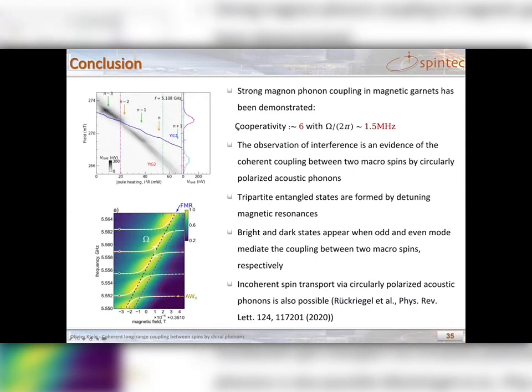So in conclusion, we demonstrate strong magnon-phonon coupling in magnetic garnets with a cooperativity of 6. The observation of interference is strong evidence that spins are coherently transferred from one layer to the other via circularly polarized acoustic phonons. We show the formation of tripartite entanglement states by detuning the resonances. Bright and dark states appear respectively with odd and even phonons. Our work was about coherent spin transport, but this can in principle be extended to incoherent spin transport as well.